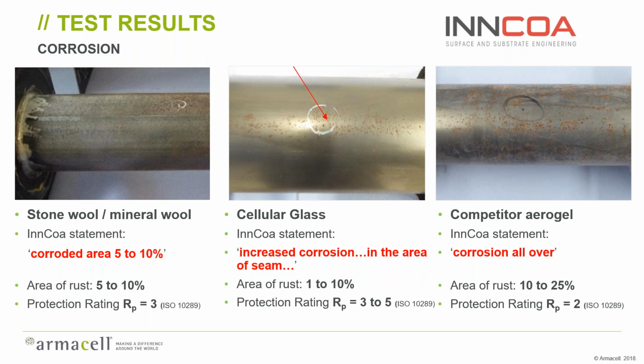I don't know how well you can see it, and I'll try to use my mouse to show it. You see some lines going across the pipe. As far as we can gather, those lines follow the lines of the creases in the blanket. So it was a stiff aerogel blanket that didn't form fully around the pipe. It didn't have intimate contact with the pipe and created creases, which then led to voids underneath. So in other words, the humidity comes through the blanket, condenses on the pipe when it's going through a cold cycle, and lo and behold, you get some corrosion occurring in those locations. That was a very, very interesting thing to observe.